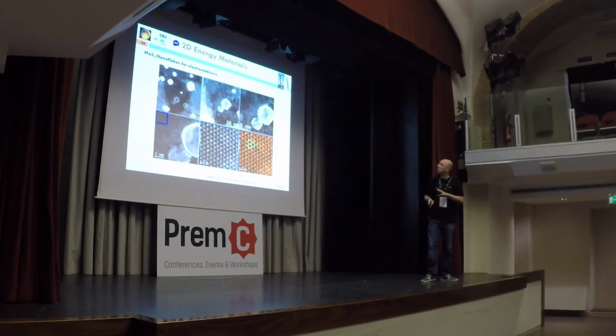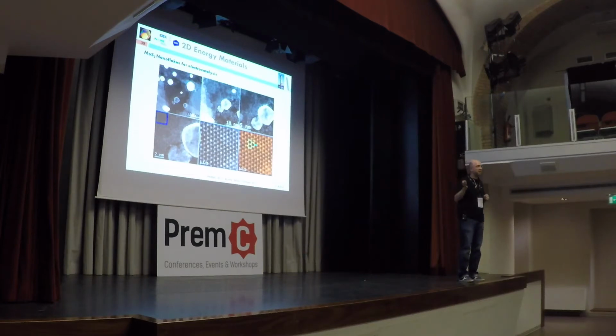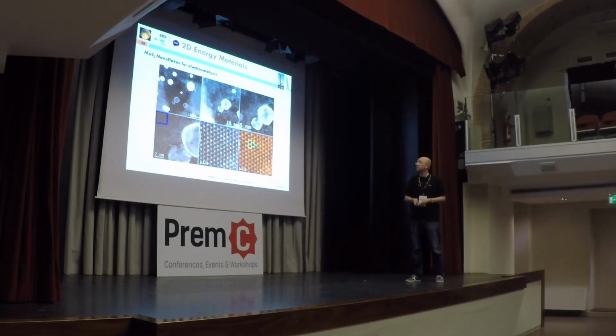So this is also important in the case of molybdenum sulfide nanoflakes. It's important to see exactly if this is a monolayer or not. It's good to identify the sulfur sites and the molybdenum sites, but the most important part is not just on top of the flake, but it's in the grain boundaries and also at the edges of the material, because those are the parts that are more active for the photocatalysis, for example.